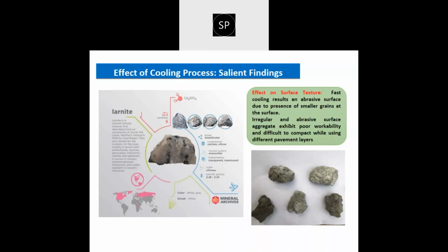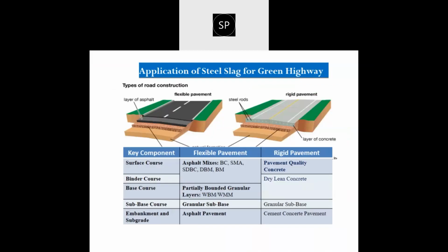The irregular and abrasive surface aggregate exhibits poor workability and is difficult to compact while using in different pavement layers. So if there is an irregular surface structure, we will face difficulty in achieving the desired degree of compaction inside the different pavement layers. Now, where can this kind of material be utilized? It can be utilized in different layers of asphalt pavement as well as cement concrete pavement. It can go into the surface course, binder course, base course, sub base course, embankment, and subgrade. This is the study which has been conducted by CRRI, and all of you might have heard or may be aware of that.